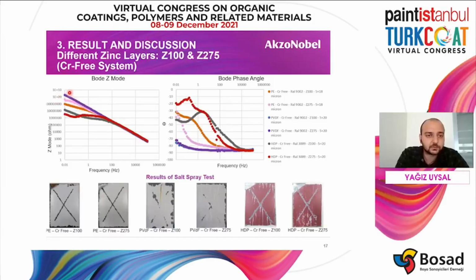Actually, we have double checked this one, and the numbers are totally different, but in the graph they are overlapping. And still, PVDF coating has the highest impedance values compared to the others, but we do not see any differences between the 2 zinc values. In the polyester comparison, zinc amount of 275 gram has higher impedance than the 100 gram, the pink one and the orange one.